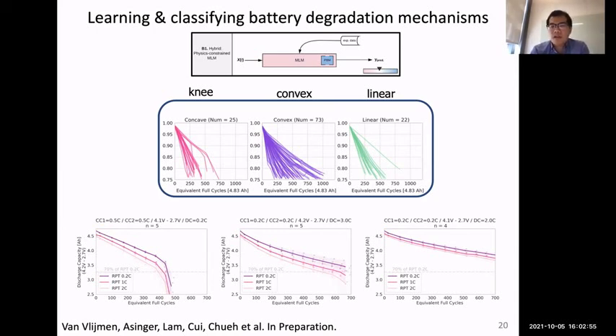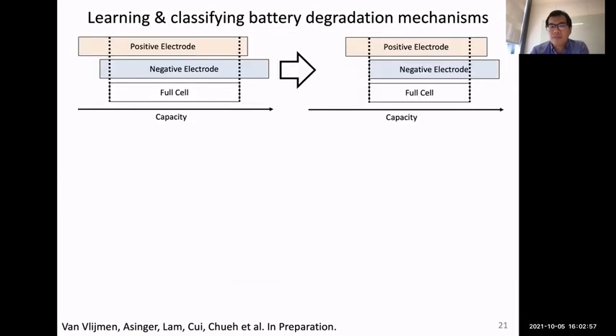And what I want to show you here is how we plug in the physics-based model. The physics-based model here we have used is the simplest possible model. It has basically two equations. It conserves the lithium mass between the two electrodes in the battery. So here I attempt to describe this schematically. As the battery degrades, what you're doing is you're moving the lithium back and forth between the two electrodes, and you lose some lithium in the process, you also lose the electrodes in the process. And knowing how the electrodes match up will tell you a lot about the degradation mechanism.